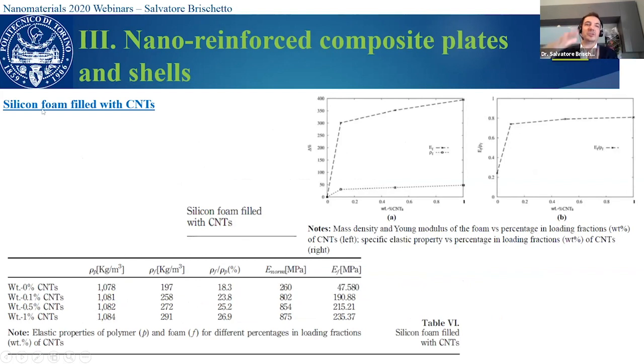We have sandwich structures with a silicon foam core, and this silicon foam core can be reinforced by means of carbon nanotubes. But in this case, we can see that when we add a different percentage weight of carbon nanotubes, the mass density increases very, very slowly, while the Young modulus has a very big increment. Okay.